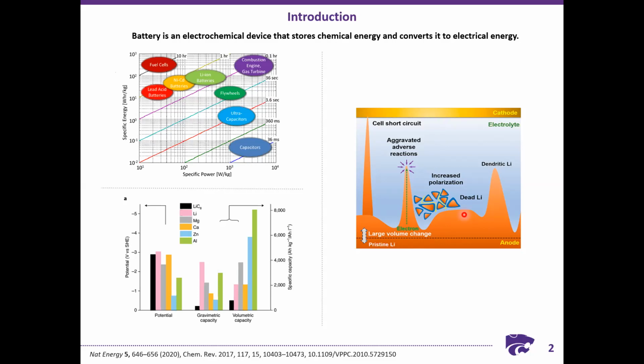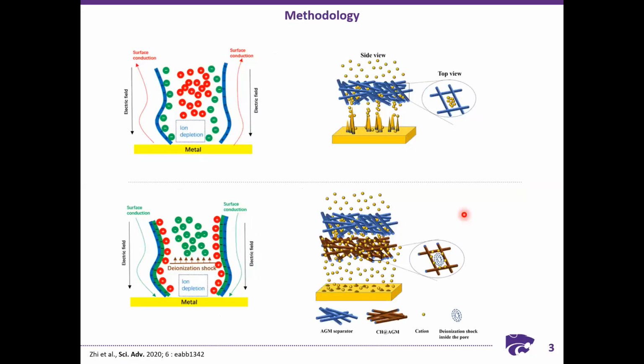So for these two issues, what the authors of this paper have done is they have used an interlayer material in between the current collector and the separator. Usually, without the interlayer, what happens is, as I said before, lithium dendritic structures form as the metal gets plated. When the interlayer is there, the concept they have conceived is coating an AGM separator with negatively charged collagen hydrolysate molecules. With the negatively charged molecules around the AGM separator, as you can see from this figure, there will be a negative charge closely associated with the AGM surface.